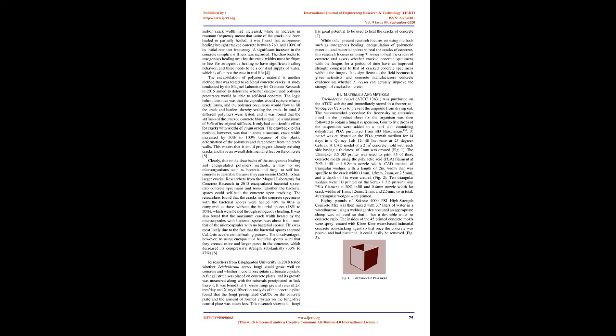The same line of reasoning could be applied to the other source of variation, which was centering the concrete sample under the ram head. Since the distance the concrete sample was off-centered under the ram head, 0.04 in, is significantly less than the width of the concrete block, 2 in, the source of variation had very little effect on the results of the experiment. In addition, the source of variation was mitigated by the steel flange, which helped uniformly distribute the load of the 12-ton press on each concrete sample.